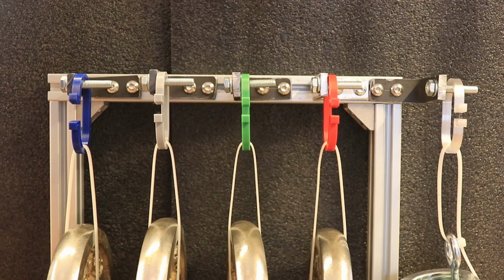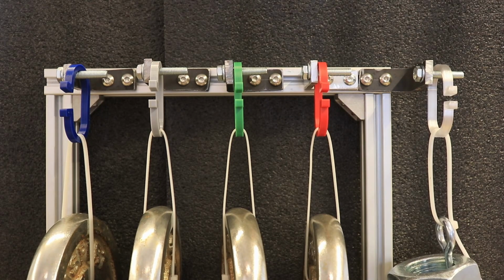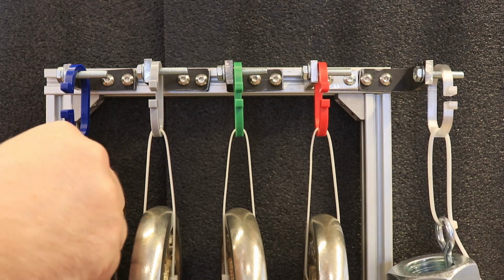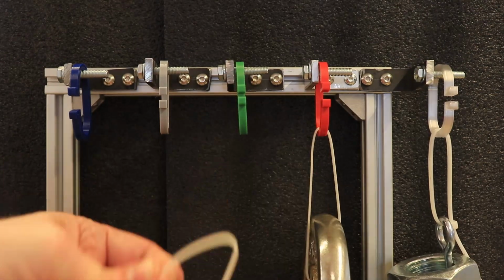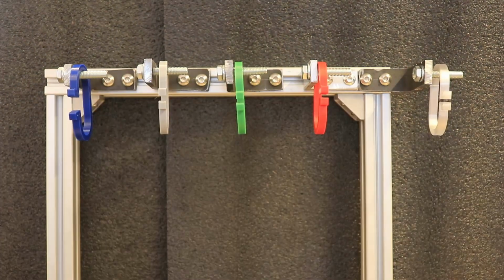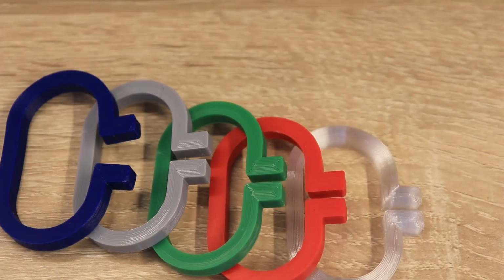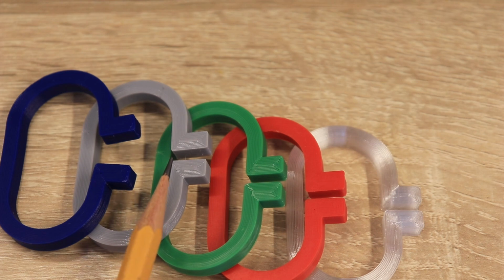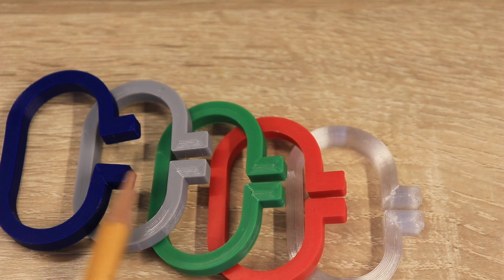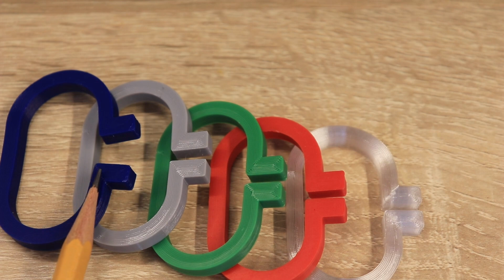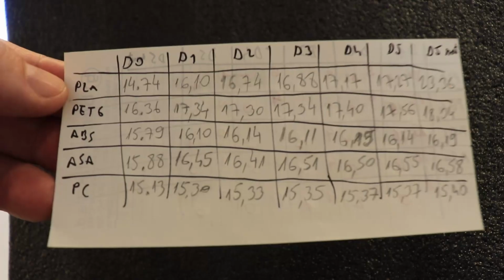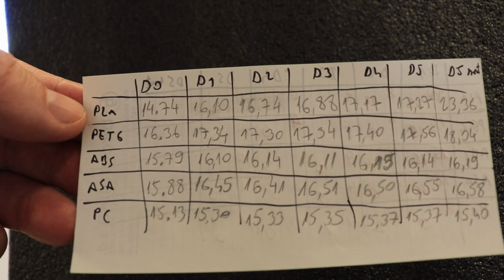And this is the position after the heated enclosure, and I can see significant deformations on PLA as I expected. And I always like to record the removing of the load. And after 10 minutes, the best is the polycarbonate, ABS and ASA very similar. I can see some minimal deformations on PETG now, but very permanent big deformation on PLA. And later I will analyze this data in Excel.